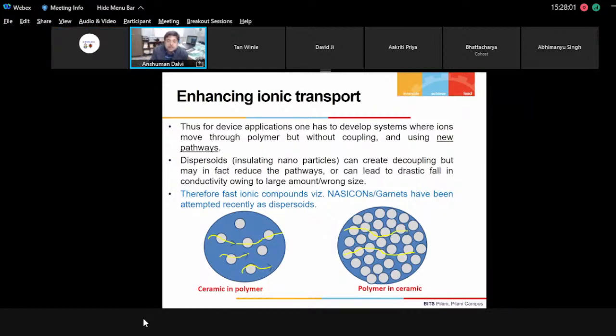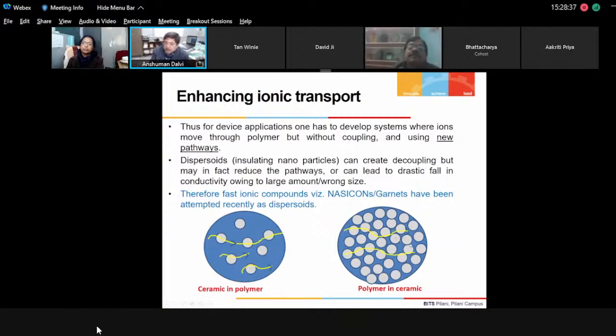But when you disperse these insulating, not insulating now, the superionic nanoparticles inside the polymer matrix, then these nanoparticles also provide pathways for the electrical transport because they themselves are also conducting. And if the polymer is in low amount, then it is about polymer in ceramic. But if the ceramic particles are in low amount, then it is about ceramic in polymer. But when you have a large amount of ceramic, then it is essentially polymer that goes into the ceramic and sits between the grains of this ceramic. So this way we can make a composite which is highly conducting, as well as one in which the interfacial transport